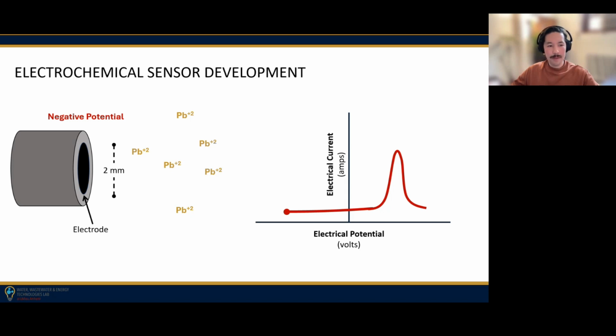And if we have lead in our water, which is a positively charged ion, so a cation, what we can do is for some amount of time, induce a negative potential on our electrode surface. So if we have a negatively charged electrode surface and we have our positively charged cations, whether they be lead in this example or copper, what ends up happening is that our lead gets attracted to our negatively charged surface and it adsorbs to the surface. So at this point, we can start increasing our potential. And at a certain point, the potential is going to increase so much that our lead is going to want to leave our electrode surface. And it's that point where we get a bit of a current response.